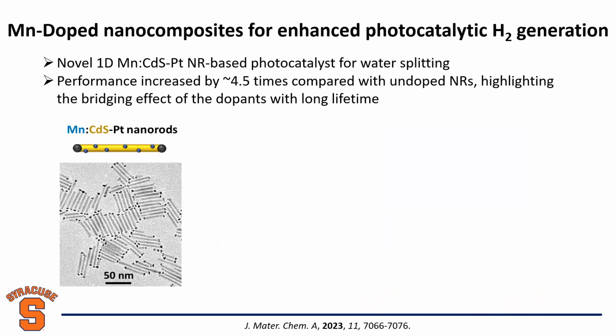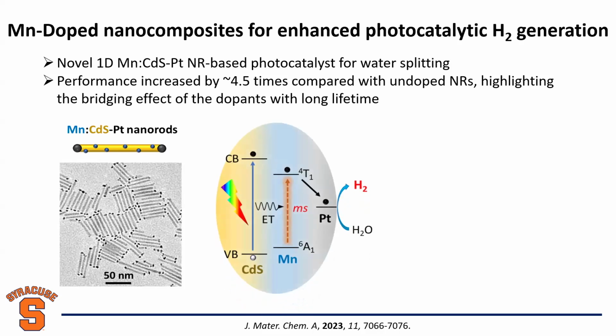Okay? Yeah, so this is our recent work. We developed manganese-doped cadmium sulfide nanorods. We decorated them with platinum particles on both sides, a kind of cute dumbbell structure, as in the TEM image. The idea is very simple, same as I showed on the last slide. We use light to promote an electron in the host lattice and sulfide, generating charge carriers, electron and hole. Then energy transfer occurs, and we generate much more stable charge carriers associated with the dopant. Then we have electron transfer, because platinum is a metal conductor. Electrons transfer to the platinum particles, which provide active sites for the water splitting reaction to generate hydrogen gas.